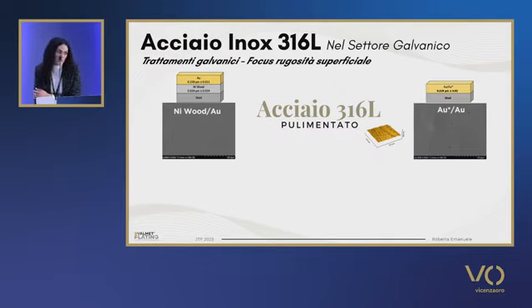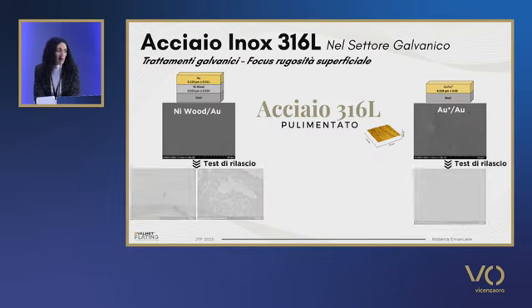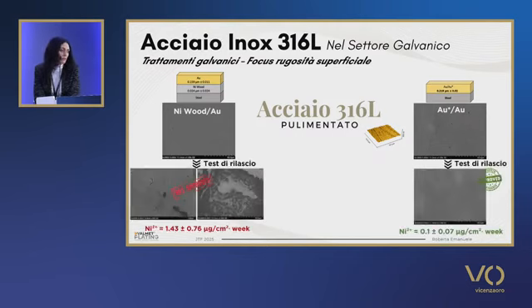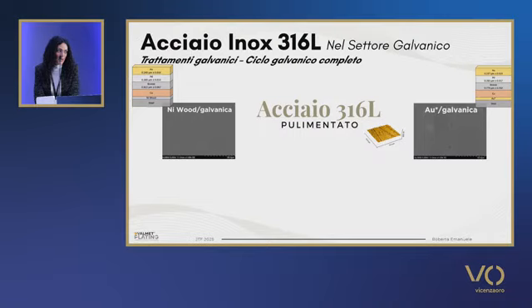We then used the other type of 316L steel that was polished, and you see that the results are quite clear. In the case of the samples that were subject to coating with Wood's nickel, we don't comply with the rule, whereas if we use gold, the results are much better. We can therefore say that superficial roughness of the sample bears importantly on the final result in terms of nickel release.